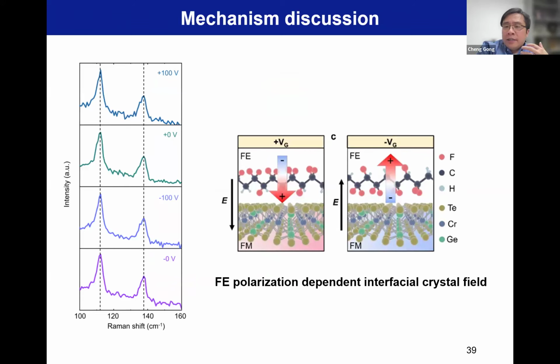And as I said, here the mechanism is based on the ferroelectric polarization-dependent interfacial crystal field. Normally in the multiferroic community, people call it composite multiferroic. It's either layer by layer ferroelectric and ferromagnet, or they synthesize an alloy, a lot of magnetic particles and ferroic particles mixed together. But anyhow, you have two phases. And normally, due to the piezoelectric effect of the ferroelectric component, they will cause a strain. And the strain will further, of course, strain the magnetic component. Because between the ferroelectric and the ferromagnet, you usually have a strong covalent bonding.